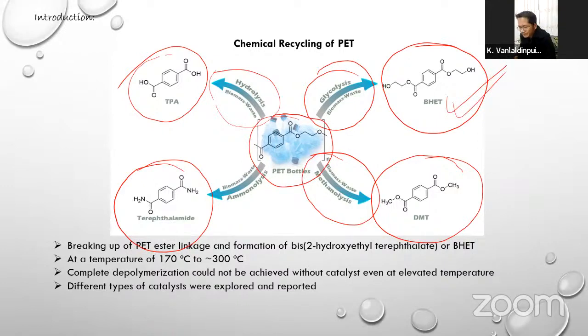Okay, so among these techniques, glycolysis is considered the best method of recycling, not only because it regenerates the monomer from which PET is synthesized, but also because it is the least capital intensive process. And it is usually carried out at a reaction temperature of 170 degrees Celsius to 300 degrees Celsius. And complete depolymerization could not be achieved without a catalyst even at a high temperature and long reaction time. Because of that, different types of catalysts were explored and investigated for this transformation.